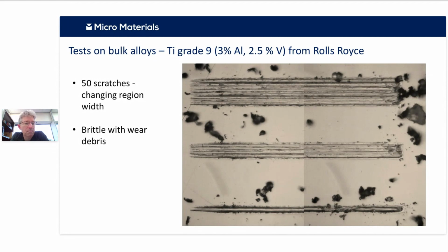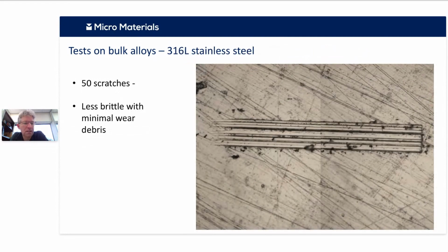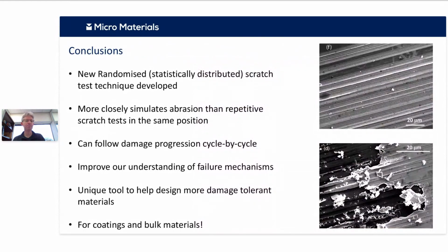out of material. And if we look in contrast, under pretty similar conditions, in this case on a more ductile material, here we're getting essentially a much cleaner response, and you're just starting maybe to get that transition towards these ductile chipping under the same conditions. So this is quite a useful way to test the abrasion resistance of new materials you're developing.